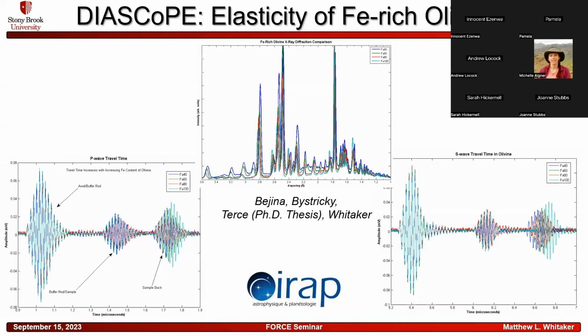So this is just a look at some of the things that we did with it originally. Some of the initial studies as we were commissioning this was studying the elasticity of iron-rich olivines. And you can see here in the top middle that the peak position of the diffraction changes with respect to iron content, which is exactly as you would expect. And we also see that the P and S wave travel times change as well with the iron content of the olivine, which again is exactly as you would expect. The travel times get longer as the sample gets slower.